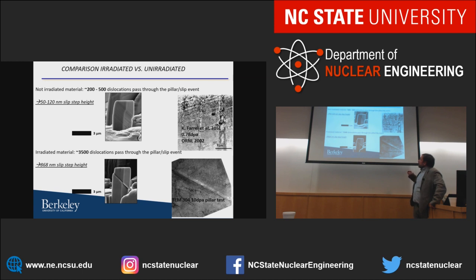Why is that? Well, it's actually well known that particular stainless steels form these defect-free channels. So when you deform stainless steel, or in general any material, it deforms along the Schmid factors, slip planes, and what have you. But if it's irradiated, you have all these very small defects in there which stop your dislocation motion. But they are dislocations themselves by their very nature, right? They're dislocation loops or stacking fault tetrahedra, any of that, which is not the same thing, but it's the same nature of defects. And so the mobile dislocation can absorb these radiation damages, leaving undamaged material behind.